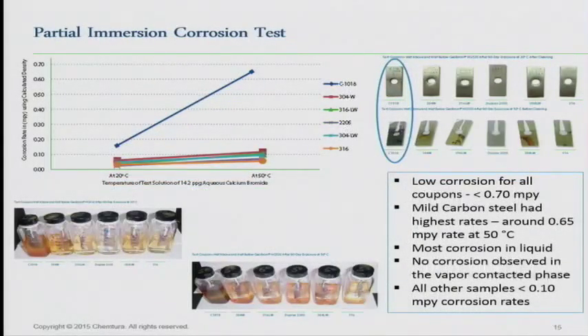Partial immersion, if there was a bigger issue, potentially because you have liquid and vapor, that would show itself here. For the most part, what we saw is what we thought we would see, which is it's not total vapor and it's not as bad as total immersion. It's somewhere in between because you have a little bit of both environments exposed to the coupons. But for the most part, again, carbon steel was the one that had the issue, but still way less than even 1 mil per year on a corrosion rate.